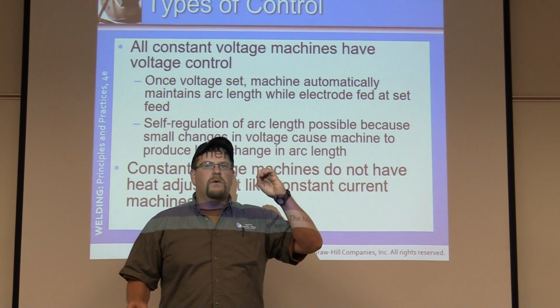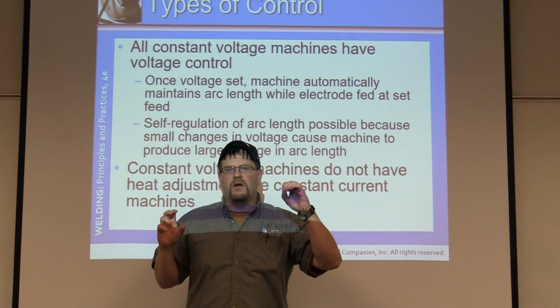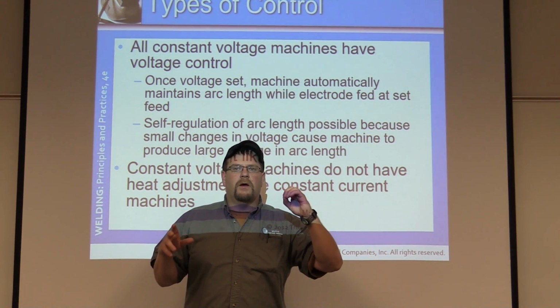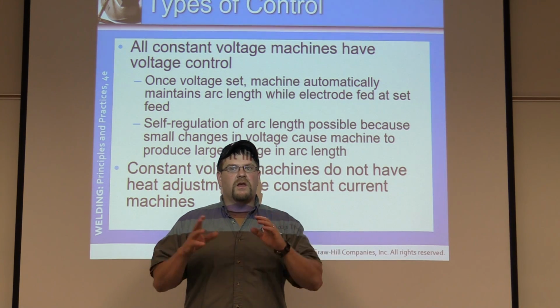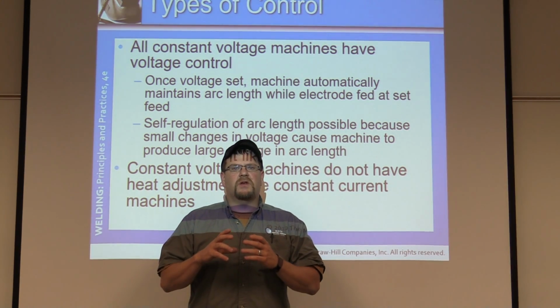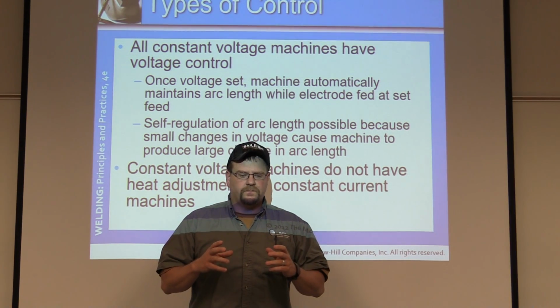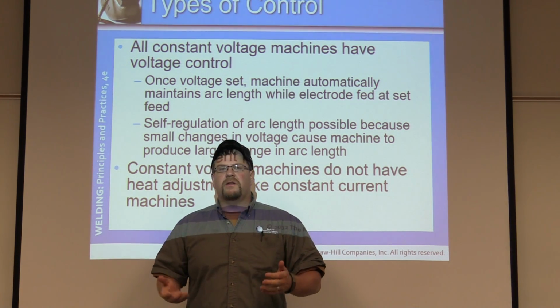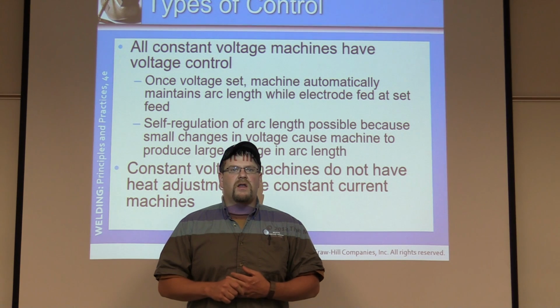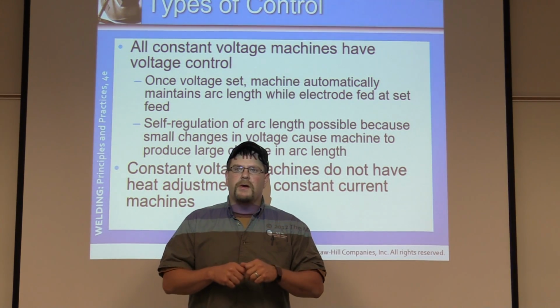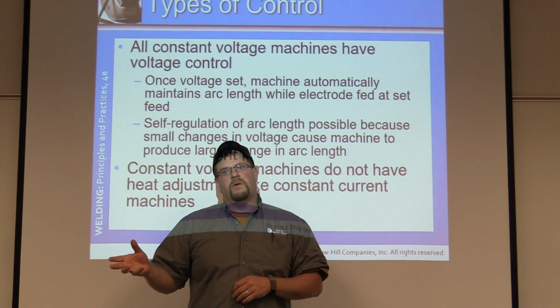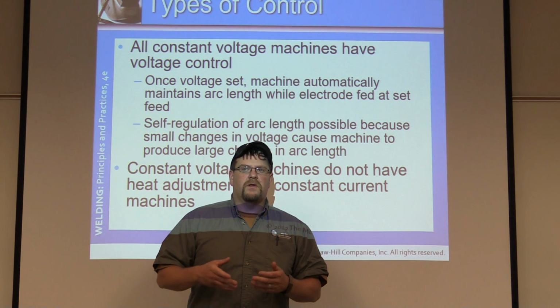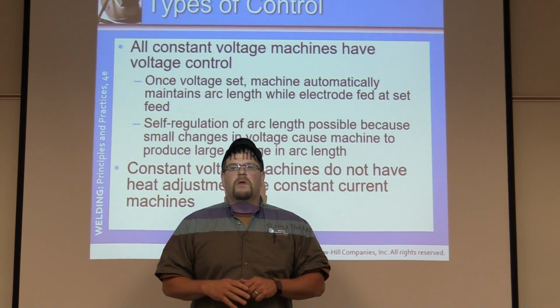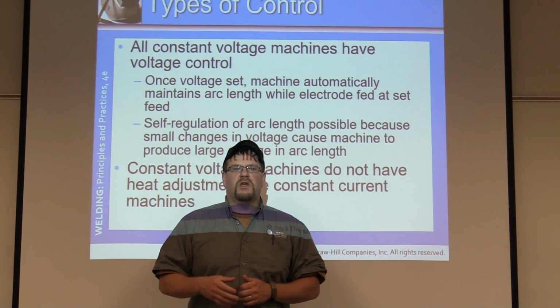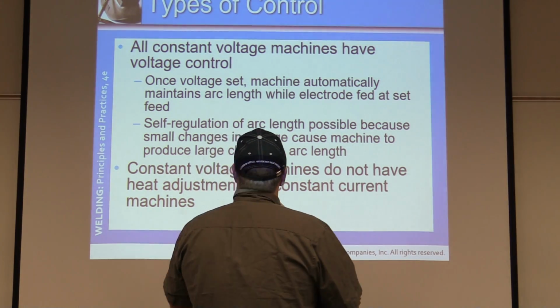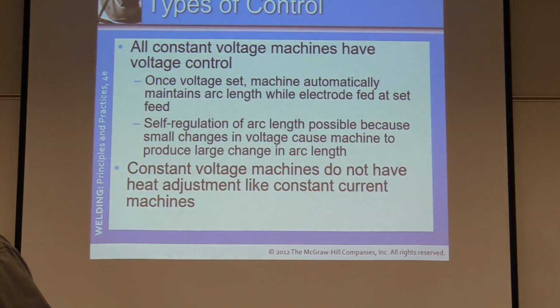So if we're at 18 volts, our range on our wire speed, our inches per minute, might be roughly between 180 and say 250. Okay. It might even be, now we're going to get there, each machine's a little bit different. Sometimes the tension on the rollers makes a big difference, along with whether the liner's worn out, what the contact tip looks like. All these little things start adding up. We have a little bit here, a little bit of voltage loss there. Next thing you know, if you're running your wire speed at 240 at 18 volts in order to maintain an arc and it's still not coming out the way you want, let's stop, let's look at our machine, see what we can adjust and what we can change to move forward. Okay? And get this back in the correct synchronized pattern that we need in order to produce a quality weld.